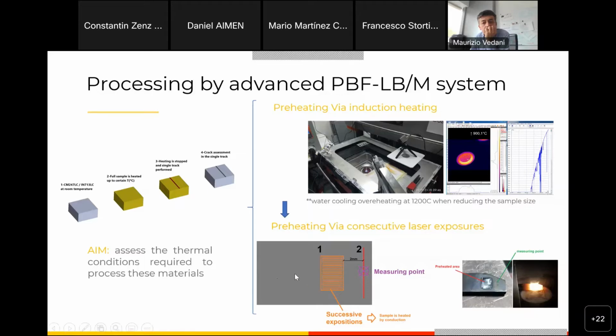So here you can see an orange hatched area, which is on top of a gray part, which will be the CM247 or Inconel 713 low carbon sample. And this hatched area is repeated consecutively until the nickel alloy reaches a certain temperature by conduction. So once this temperature is reached, we stop these hatching repetitions, and then we perform a single track about 2 millimeters far from this area, which was heated as well. As you can see here, this purple circle was the measuring point where we were measuring the temperature before, during, and after the melting process of the single track. In this way, we were able to measure at which temperatures this cracking phenomenon is mitigated. Mauricio, if you can skip to the next slides.